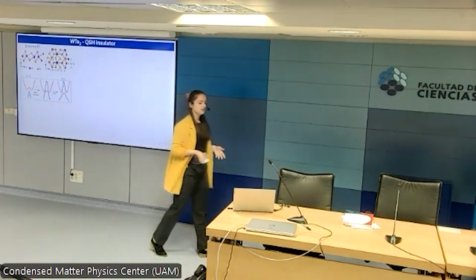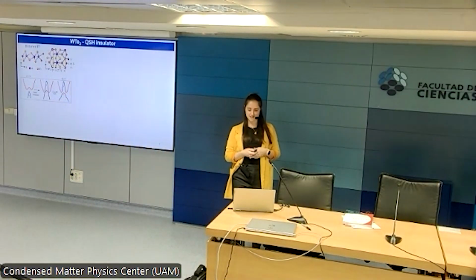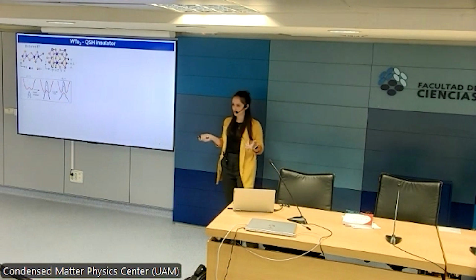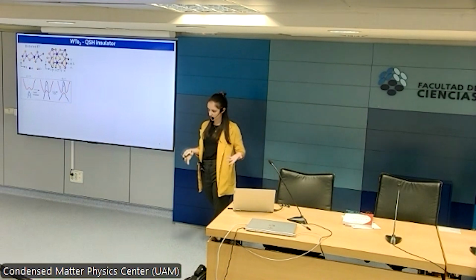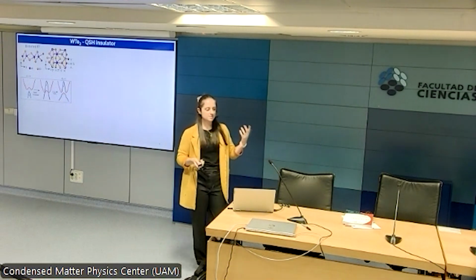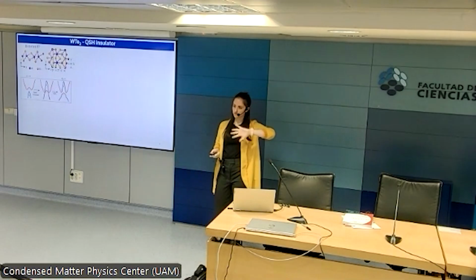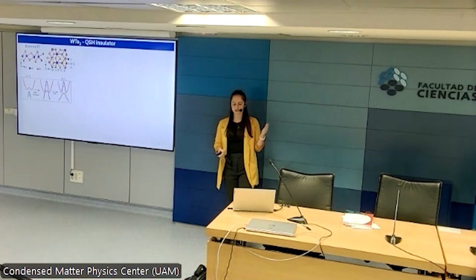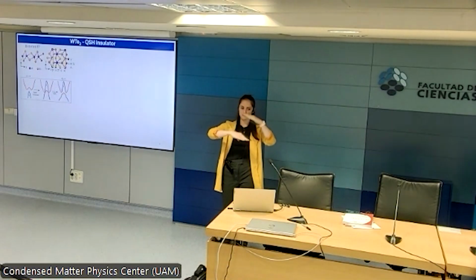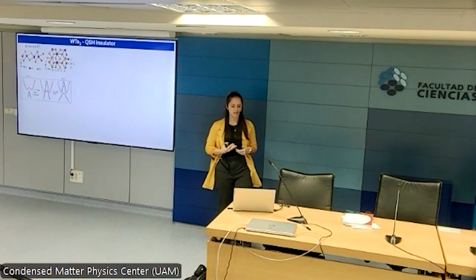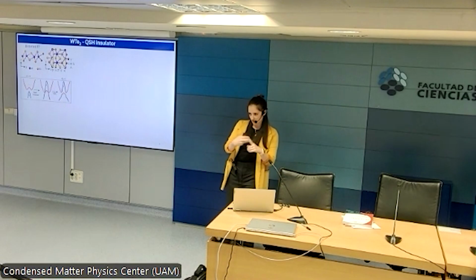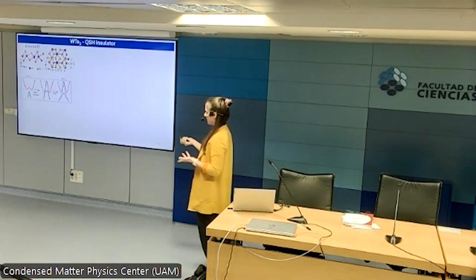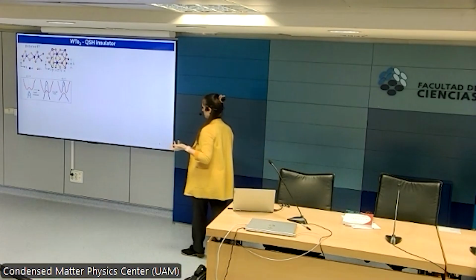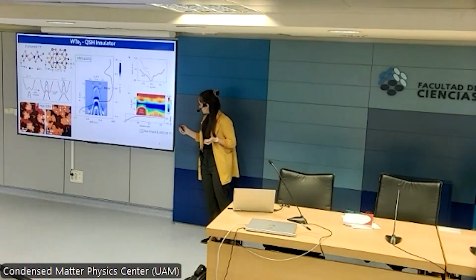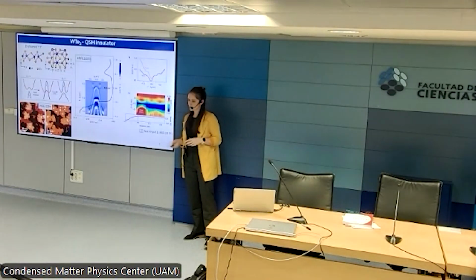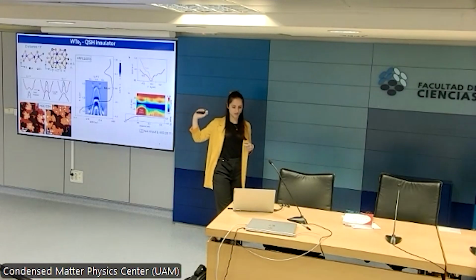Now, this material, at the very beginning, was predicted to be a quantum spin Hall insulator, so a topological insulator, pretty much. And this is because the bands that you have at the Fermi level from tellurium and tungsten have different parity, so spin-orbit coupling would make them overlap, but because of the different parity, the crossing is avoided, and so you have the opening of a topological band gap and the formation of topological edge states. This was demonstrated as early as in 2017. This work is from the group of Professor Mike Crommie at Berkeley.